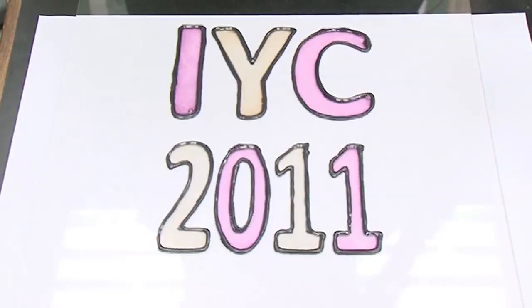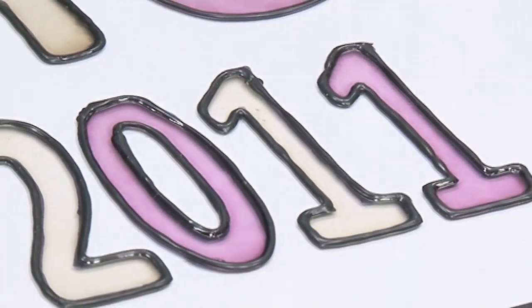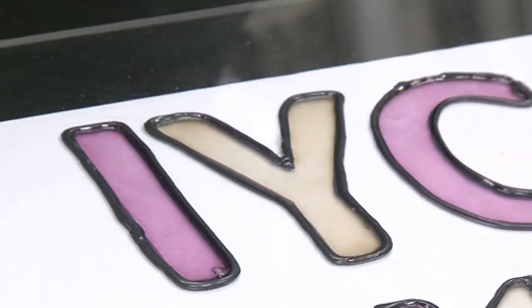It's probably quite small, maybe a nanometre — ten to the minus nine metres — or might be slightly more. But it's really quite small, a few tens of thousands of atoms or less. The silver is probably a similar sort of size. I know, because my research group has made nanoparticles of silver — can't afford gold. We've made nanoparticles of silver, and around seven to ten nanometres diameter gives this sort of colour.